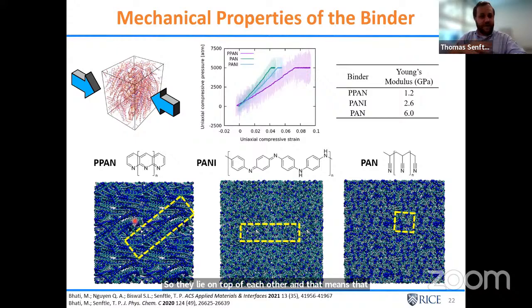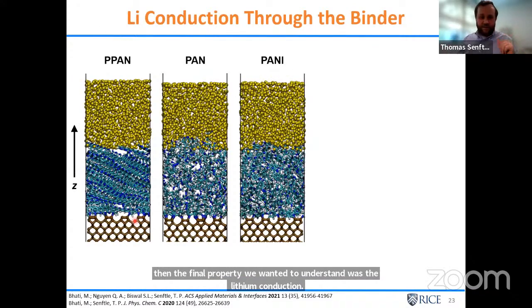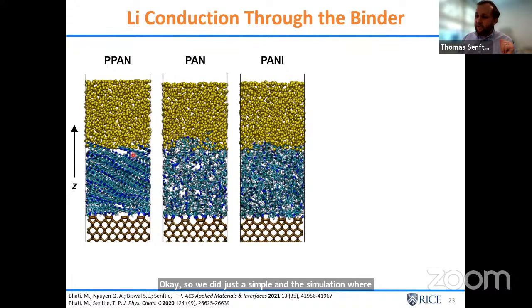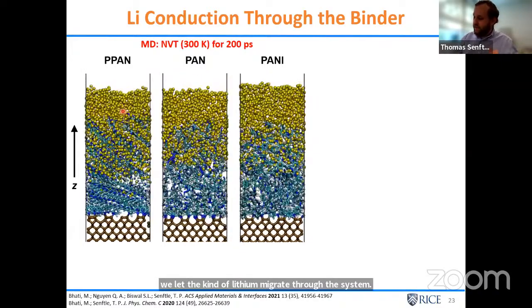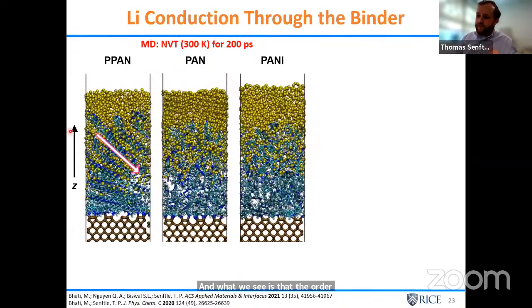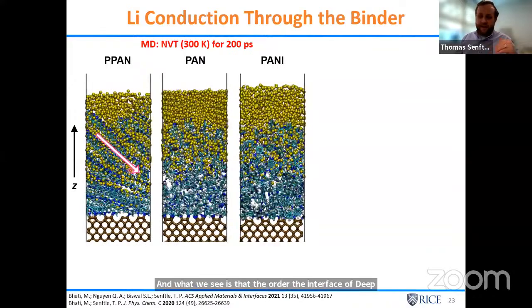So again, the collective behavior is different than what we would expect from just a single chain. And then the final property we wanted to understand was the lithium conduction. Okay, so we did just a simple MD simulation where we have our equilibrated interface. We start with lithium, and we let the lithium migrate through the system. And what we see is that the ordered interface of p-pan creates these channels that allows the lithium to get into and out of the system really fast.